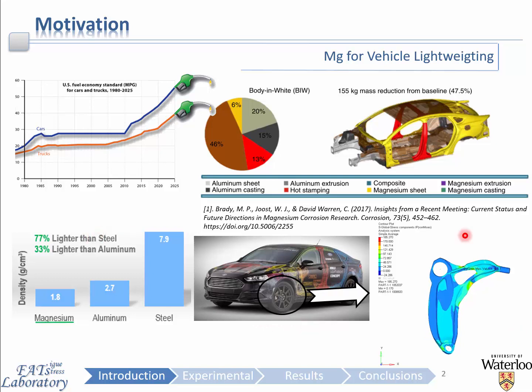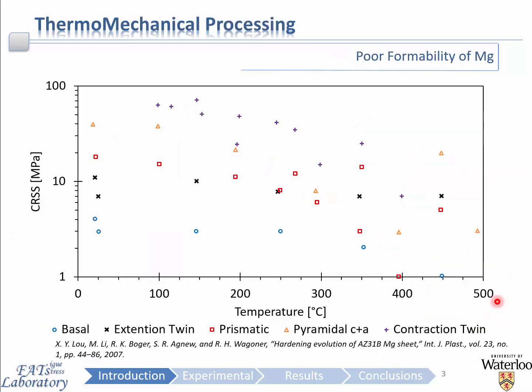Seen on the right is an elastoplastic simulation of the critical service load cases for the component which we intended to forge, which is a front suspension component on a passenger vehicle. You clearly can see that the deformation is highly three-dimensional and the resulting stress state is highly multi-axial, which is why we're interested in the multi-axial behavior of magnesium in the first place.